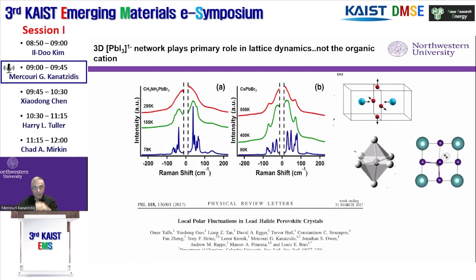Raman spectroscopy also confirms this. If you do a Raman spectrum on these materials at room temperature, you see a very broad Raman spectrum. And that doesn't make sense because these are crystalline structures and they should have well-defined peaks. You do see the well-defined peaks when you go down to very low temperatures, like 79 Kelvin. But at room temperature, you see nothing, very broad. Basically, it looks like a liquid. If you take a liquid and you run the Raman spectrum, this is what you're going to see. So in a way, it's liquid-like behavior, even though it's a crystal, and it vibrates at all frequencies. And that happens for two reasons: because the lone pair goes off-center, and also the A-site cations can be moved off-center as well.